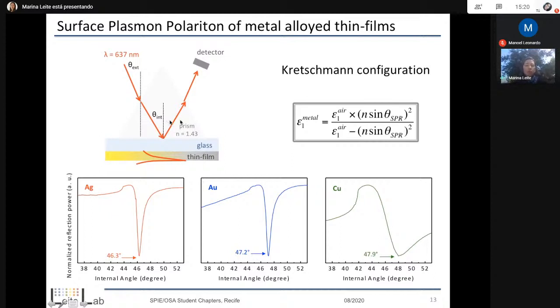So literally what we need is a thin metallic film deposited on a glass substrate, in a prism with a well-known refractive index. And what we're measuring here is basically the surface plasmon polariton propagation. And I think this is really neat. So essentially, we come in with light. You can choose whatever wavelength you want. And you better know well the thickness of the film. That's really critical, so that we can then have this attenuated total reflection condition here. And we can then excite the surface plasmon polariton here, at the thin film and dielectric, here air. So essentially, this experiment is what we call the Kretschmann configuration.